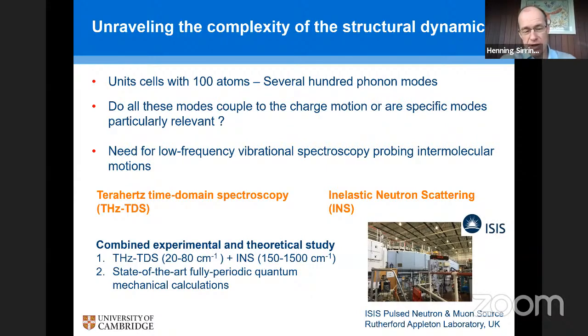very complicated unit cells. The molecular systems often have 100 atoms in the unit cell. So that means there must be 100 phonon modes or several hundred phonon modes. And so effectively, you'd have to worry about what contribution each of the phonon modes makes to this dynamic disorder. Each phonon mode will lead to fluctuations in the transfer integral, and you might wonder which ones are the ones that are most strongly affecting the transport.